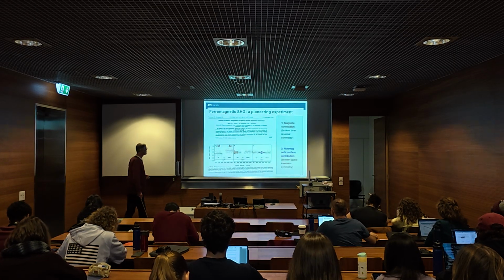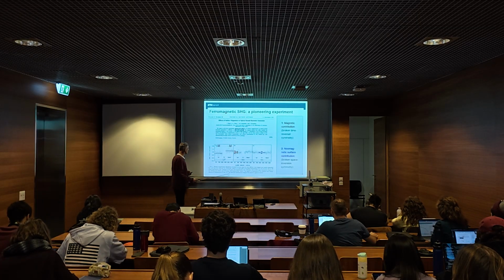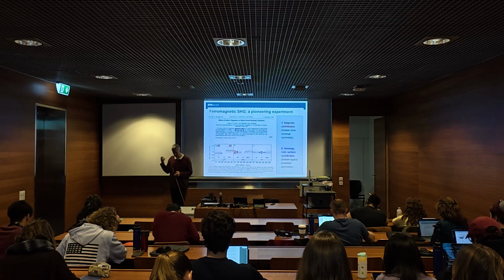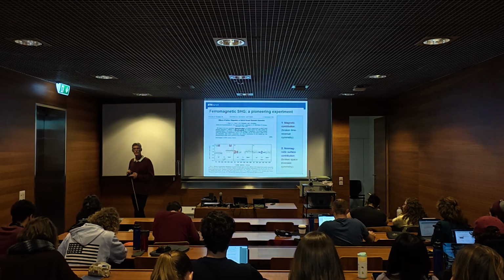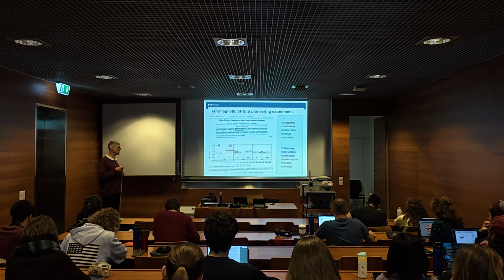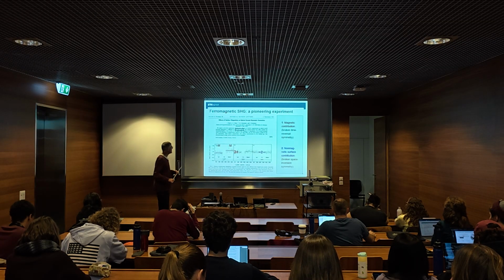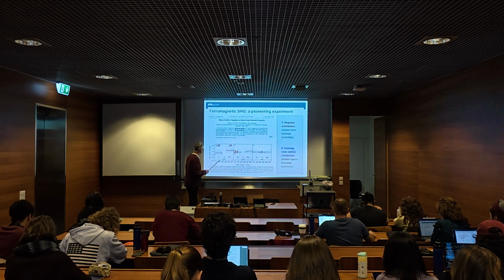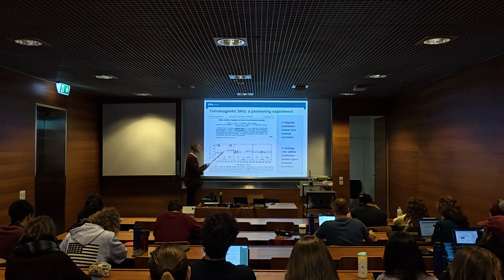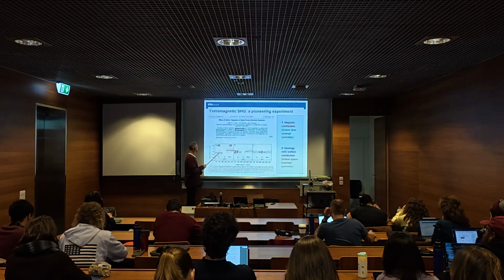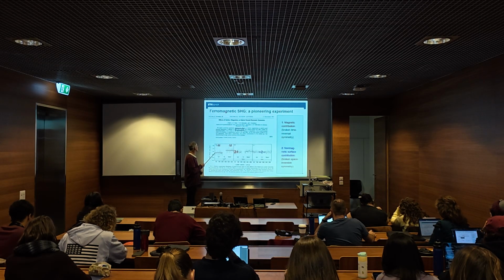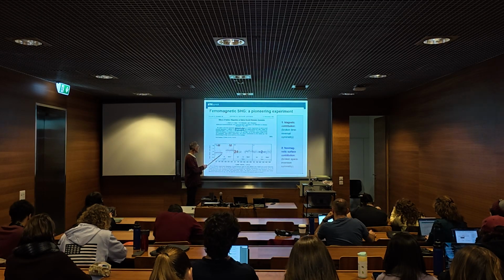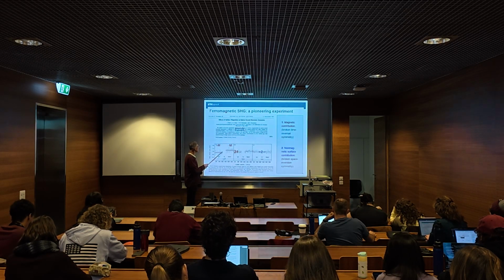This is then how it was used for the first time, this nonlinear optical process, to detect ferromagnetic order. Remember, ferromagnetism typically used this magneto-optical Kerr effect that I had on the earlier slide, but this frequency doubling technique can also do it. So you take a ferromagnetic iron surface, minus or plus magnetize it in a magnetic field, and then you see that the emission intensity of the frequency doubled light is a little bit different for plus and minus M. So it's very noisy, but the average clearly is different.